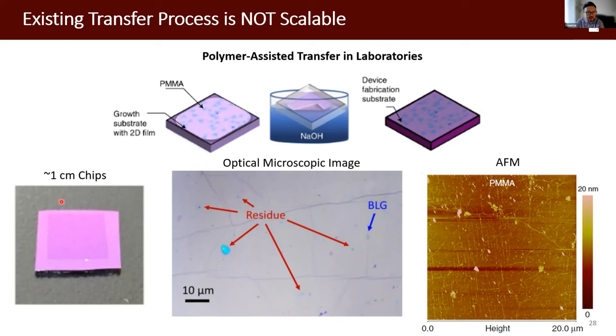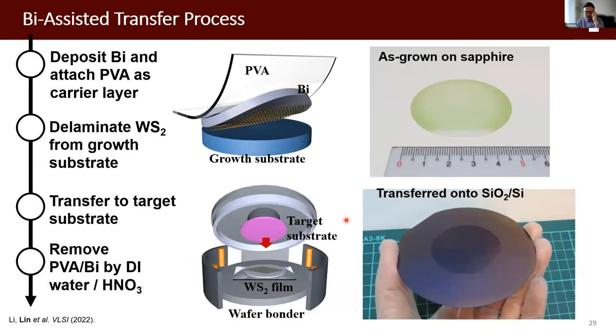We can only comfortably transfer 1 centimeter scale samples. And if we look at the characterization, there are a lot of polymer residues and wrinkles on the substrate. We developed a more scalable approach. So we insert a metallic layer in between the polymer and the 2D material. The metallic layer is more mechanically strong, and it can also offer better interaction, better adhesion with the 2D materials. And then we combine this approach with a commercial wafer bonder for silicon technology, so we can easily transfer wafer scale 2D materials with good uniformity and free of wrinkles, tears, or defects onto the targeted substrate.